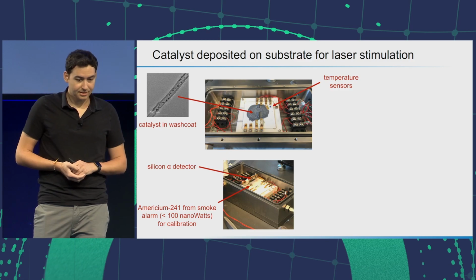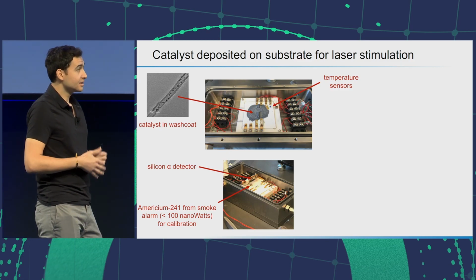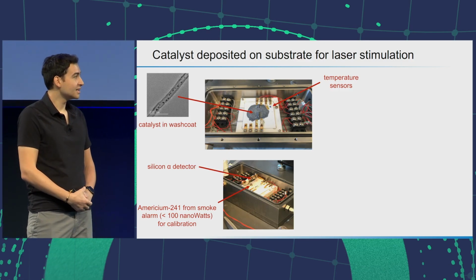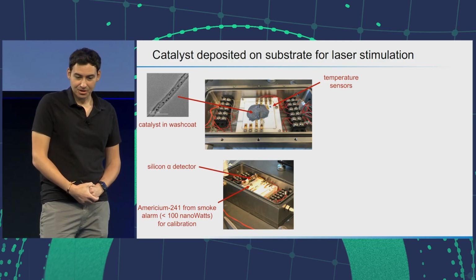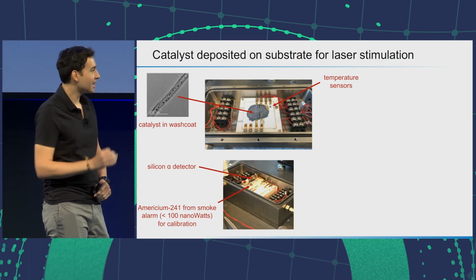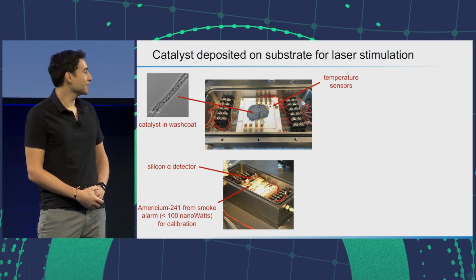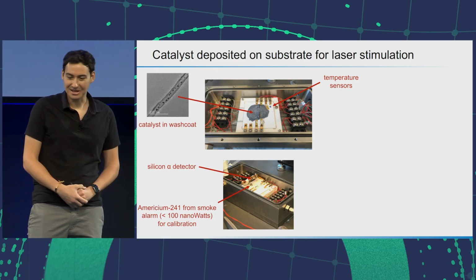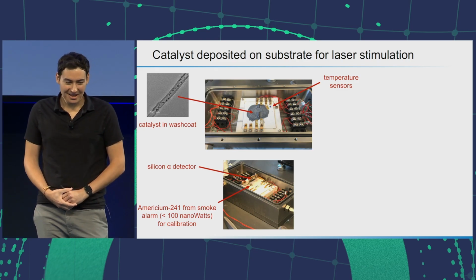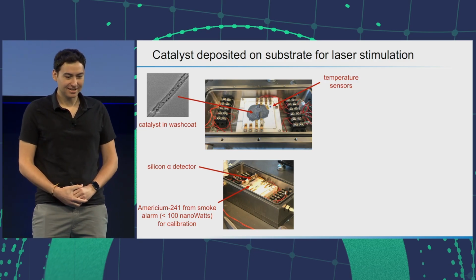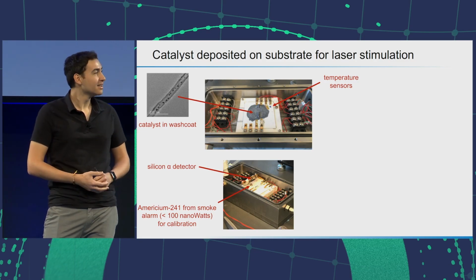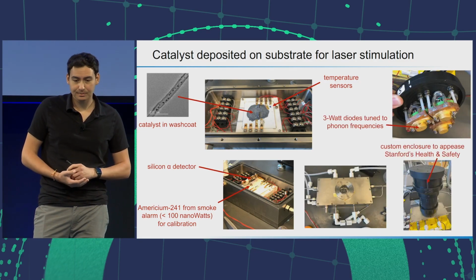We got a silicon alpha detector. It detects charged particles, so the glorified solar cell, really. And we took apart a smoke detector to get a little bit of americium to calibrate our detector, which Stanford was not very happy with us taking apart. But in any case, it gave us a calibration down to 100 nanowatts of these detectors.